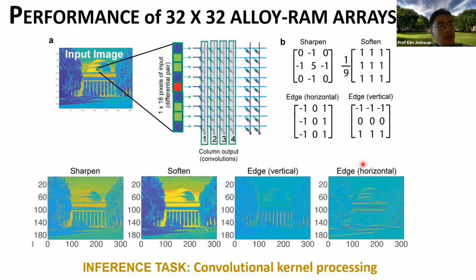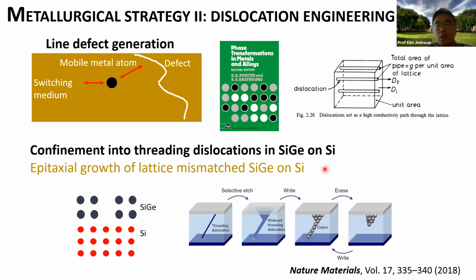Okay, let me introduce another strategy that we have been using in our lab. This strategy is to apply dislocation inside the switching medium. This mechanism has already been discussed: if there is a dislocation in the solid, then this will be the preferred path. So we have grown silicon germanium on silicon, where there is a threading dislocation, vertically aligned from top to bottom, where you can confine the metal ions inside this dislocation.